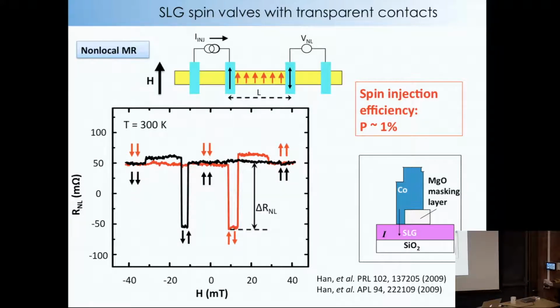So what you do is you'll start with this type of geometry, and you'll have these 2 electrodes, the injector and the detector. You'll start with them, say, parallel. A large negative field makes them parallel. You start increasing the field, and at some point, one of these 2 ferromagnets will flip over. And then you see a big jump. And then finally, at another field, the second one will flip over, and then you'll see another jump. So they go from being parallel pointing down to anti-parallel to parallel pointing up.